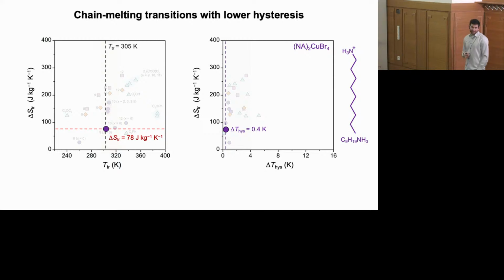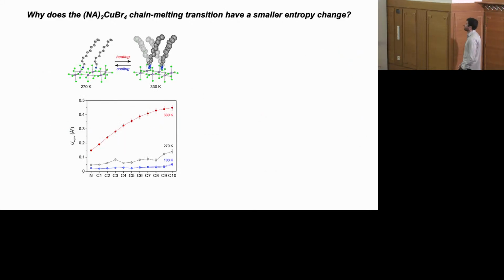But this material undergoes a similar type of order-disorder phase transition with a relatively low entropy change, but really low thermal hysteresis. So reversibility on the order of less than half a Kelvin.